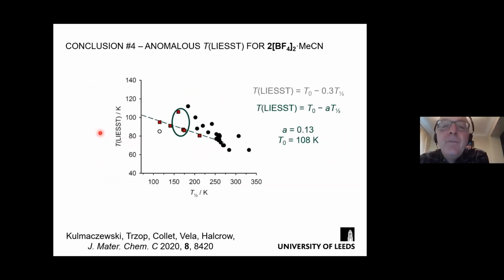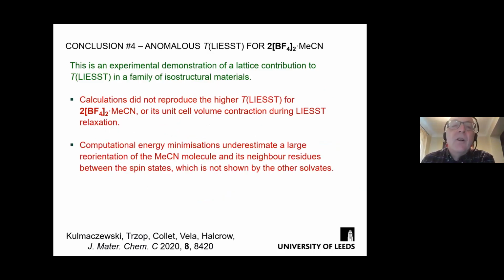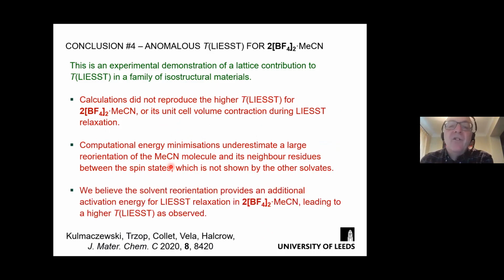And then lastly, why do these materials especially have different T LIESST values? I think it's because of the large structure change of the acetonitrile molecule, which is not reproduced by the DFT calculations. And this gives an additional kinetic barrier for the LIESST relaxation that we do not see in the other crystals. So that is everything that I want to tell you, and thank you for listening.